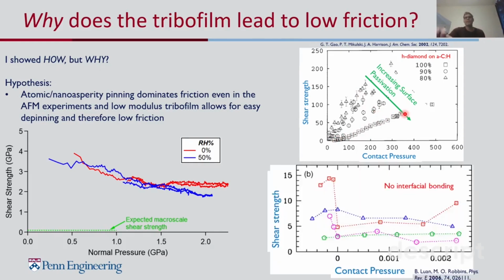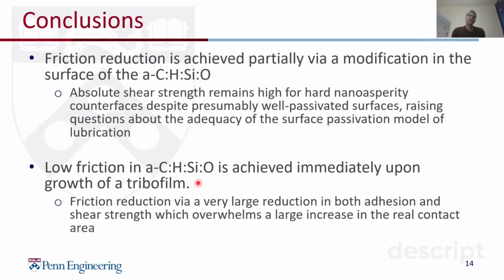And again, we'll rely on simulations from the Robbins group. And this is a molecular dynamics simulation where the bonding potential was such that no interfacial bonds could form across the surface. And therefore, any contribution to the shear strength is just atomic pinning between atoms on each side of the interface. And in that case of an atomic pinning dominated system, what they see is that the shear strength is approximately constant with the contact pressure. And this is very similar to what we see in our nanoscale experiments. So this is why we hypothesize that what's actually happening in our system is friction that's dominated by pinning of some sort.